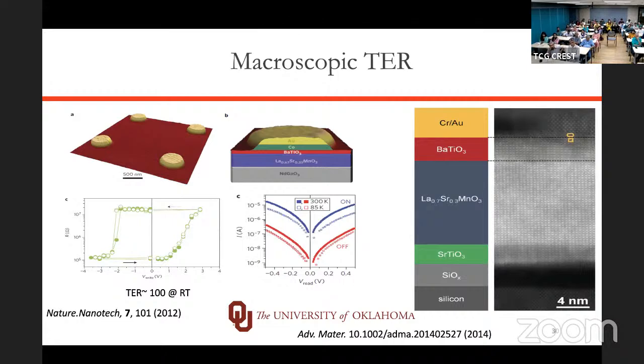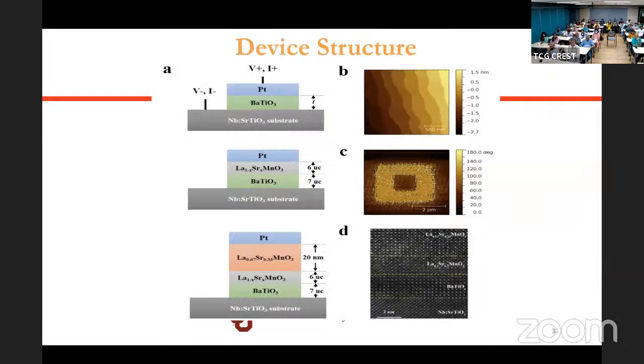So we started studying this in our laboratory by making this type of device structure, where we take a simple structure like platinum, barium titanate, which is ferroelectric, and then the bottom is niobium-doped strontium titanate. Just think of it as a metal. So metal, ferroelectric. Now I can add an extra metal layer in the middle, which is lanthanum strontium manganese oxide. All of this is done at the unit cell level. We can control these layers to one unit cell accuracy. For example, this is 7 unit cells of ferroelectric, 6 unit cells of the metal on top, in this case 20 nanometers, 6 unit cells, 7 unit cells. And you can see this crystal structure. There's a cross section showing that atomically, the entire thing is a beautiful single crystal structure.